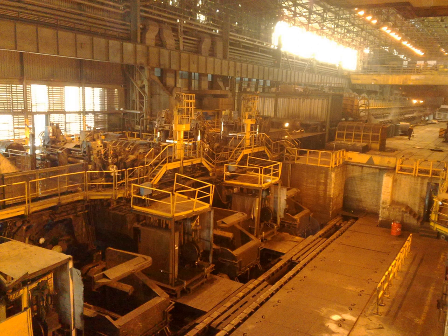The iron plant complex has 10 main production line units. The rest are auxiliary and backup units. Iron ores with large grains from Golgahar are converted by ball mills in the pelletizing plant. After mixing with Chadormalu's smaller grains and bentonite in blending machines, it is changed to pellets, diameter 6 to 25 mm, and screened by a two-story roller screen. Pellets solidify in an induration tunnel or furnace at 1280 degrees Celsius.